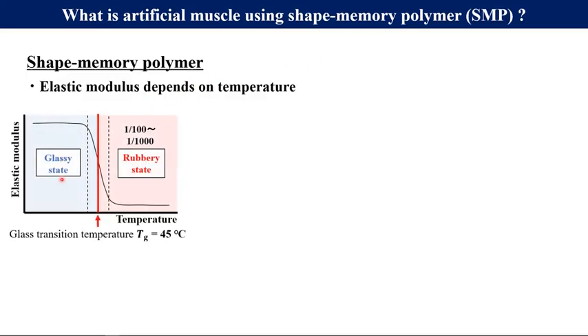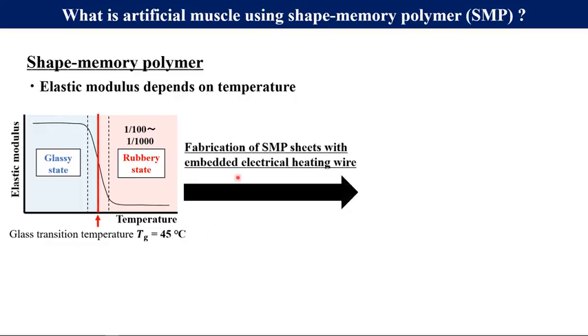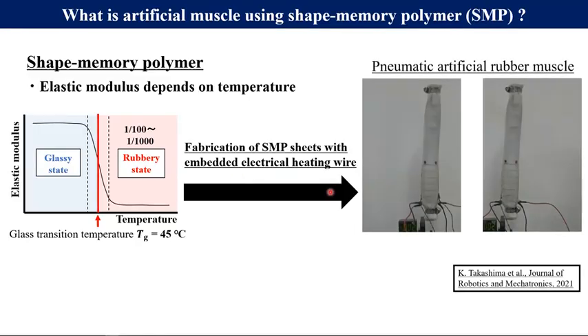As shown in this graph, when the SMP is heated above Tg, its elastic modulus changes to 0.1 to 1% of that below Tg. So using this feature, we fabricated SMP sheets with embedded electrical heating wire that can arbitrarily control temperature changes. And then we attach these sheets on both sides of the artificial rubber muscle in order to control its behavior.